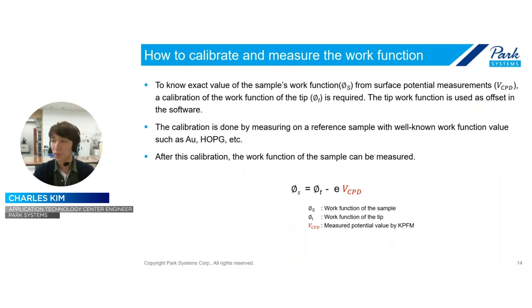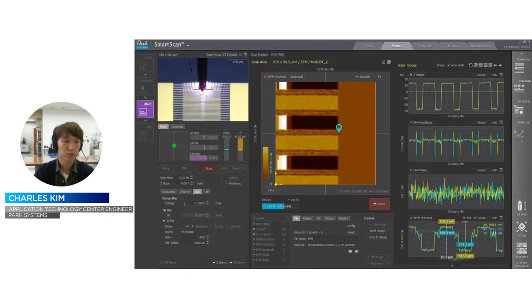And the last is to calibrate the work function. Previously, I said there is a small offset. That offset comes from the cantilever work function. So to compensate for this value, we need to measure some sample whose work function we already know. If we already know the work function of the sample, then we can use it as a reference. So for example, here,